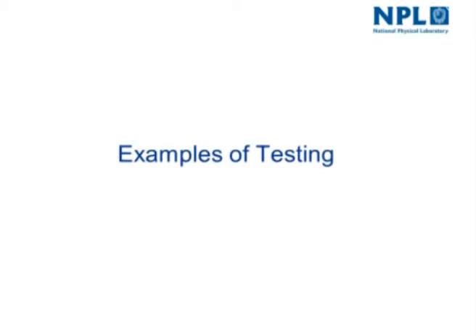You can then use Hertzian contact theory to get an initial estimate of the start contact pressure, and that gives you an estimate. The problem with that approach is that almost instantly in a test you lose that because you get some wear and the contact area changes with time. So there's not a simple answer to that, so even that simple question gives you some issues, and I've actually got some slides, I didn't have space to put those in, that illustrate that sort of issue.